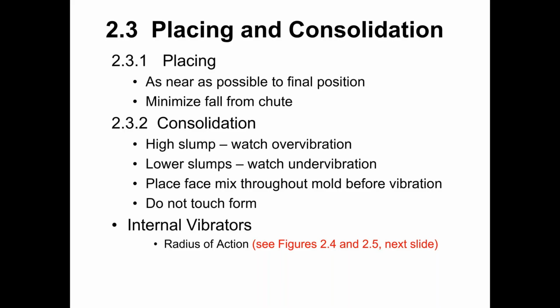All right, consolidation of concrete. If it is a high slump mix, then we need to be careful to avoid over vibration of the concrete. If it's a low slump mix, then we need to be careful to avoid under vibration. So generally, we're going to be pouring mixes today that would fall more in the higher slump range than the lower slump range. So over vibration would be our biggest concern. Another rule of thumb for an architectural face mix is that generally you want to place the full face of the panel from one batch of concrete.